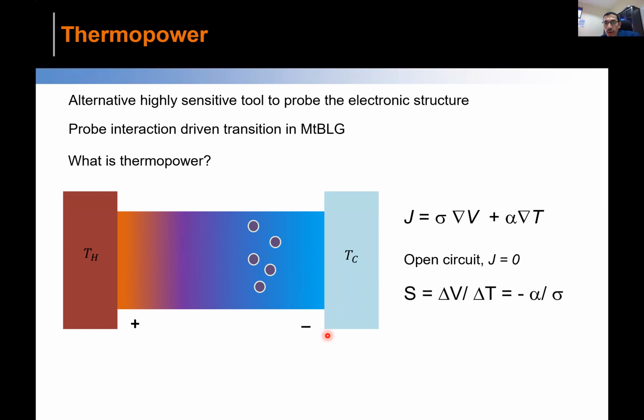What you need to know for thermopower is that the current is proportional to the gradient of the chemical voltage and the gradient of temperature. The thermopower is nothing but the open circuit voltage you measure across the sample, which means the current is zero. That gives you the relation that the thermopower, or Seebeck coefficient, is the generated voltage delta V divided by the temperature difference. This is called the thermopower or Seebeck coefficient.